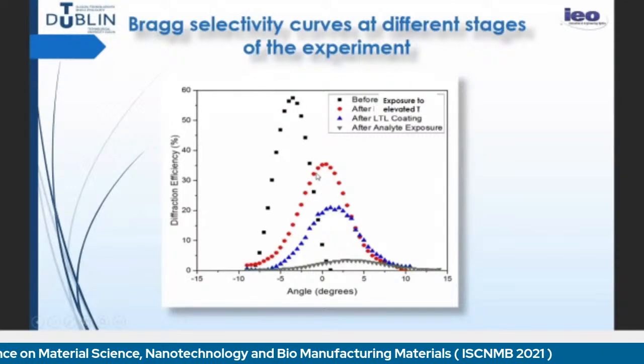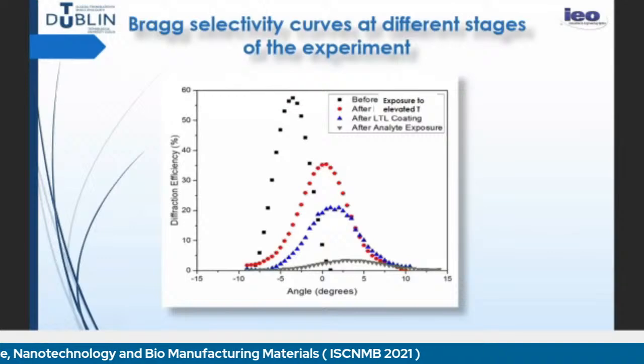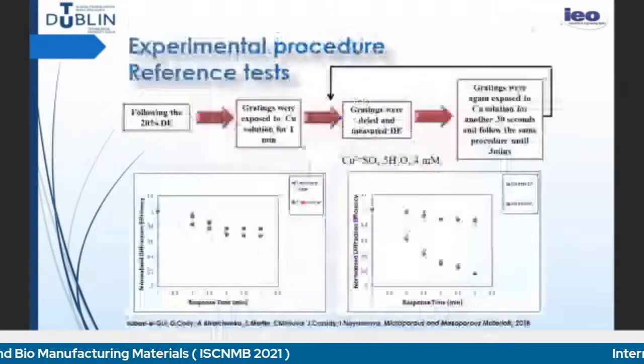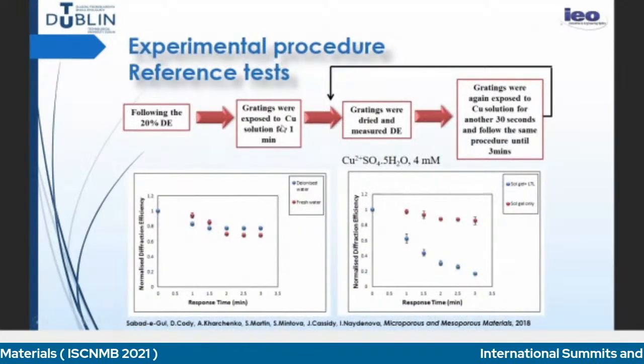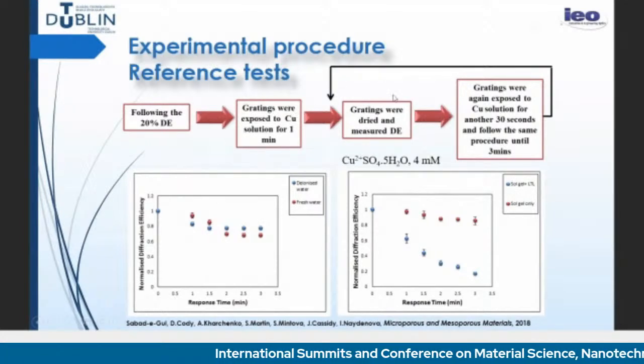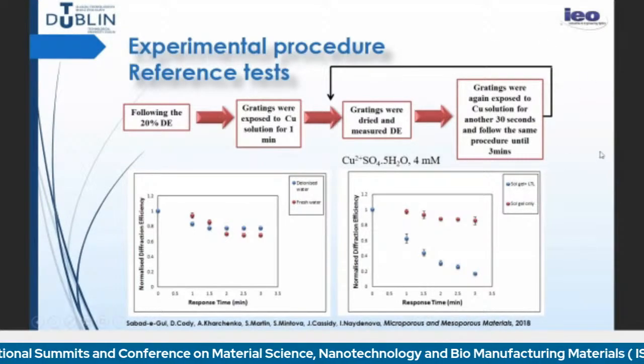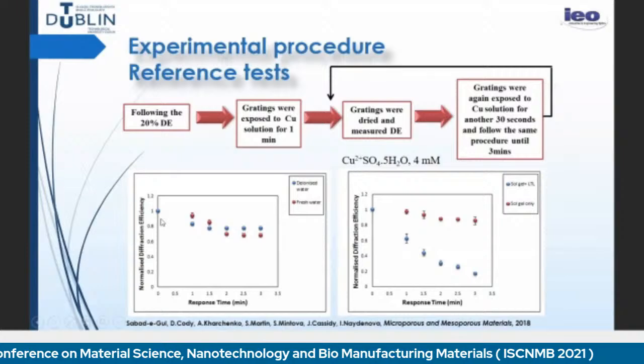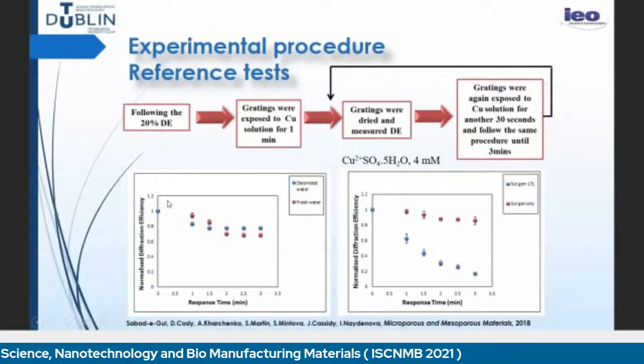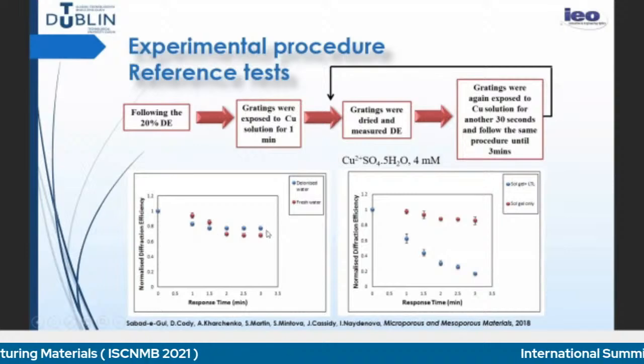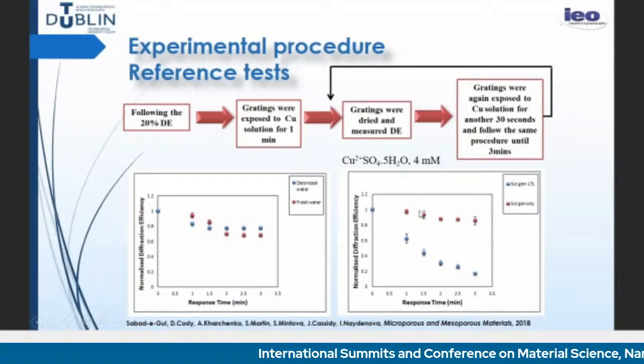And then we exposed to analyte and observe how the diffraction efficiency changes. So this is the sequence of events. The grating is exposed to the copper solution for 1 minute, then it's dried and measured, and then it's exposed for another 30 seconds, and this repeats. Here, these are the reference results where we have fresh water and deionized water. There is some background change, of course. And then we have the Sol-gel only, and Sol-gel plus LTL exposed to copper.